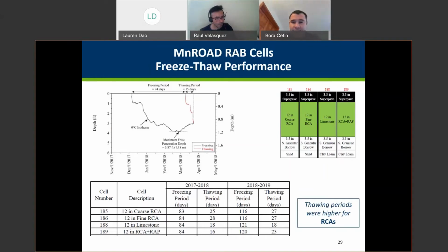And this is related to two things. Of course, the first is thermal conductivity. We hope that in future studies this will be measured for these materials. But the current data shows that absorption is very important. The higher the absorption of your material, the more water it will absorb and keep, which will turn into more ice. And of course, that higher ice content will take more time to thaw. That's why we see higher thawing periods for RCAs compared to 12-inch thick limestone materials. Next slide, please, Ro.